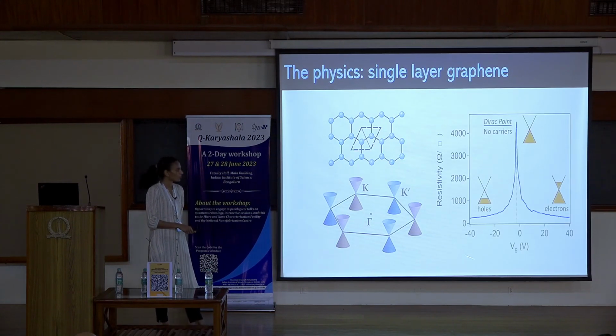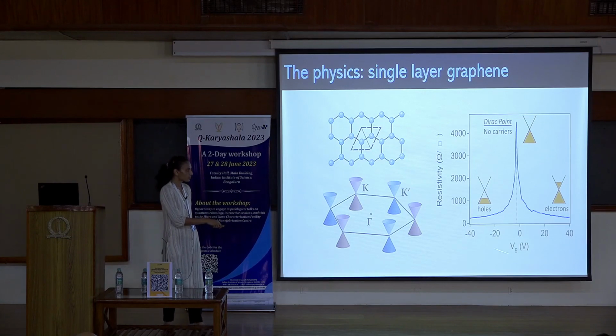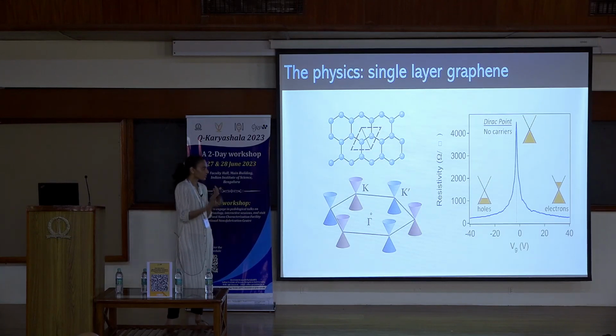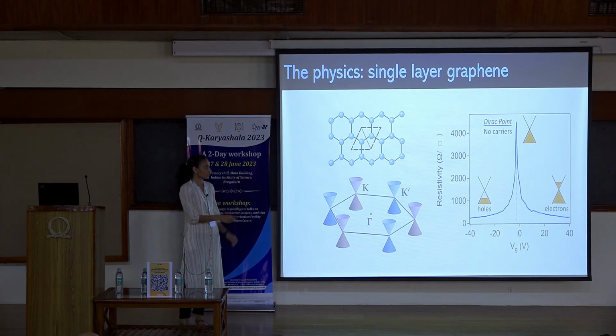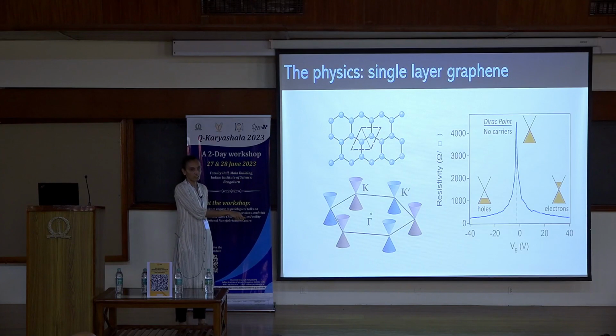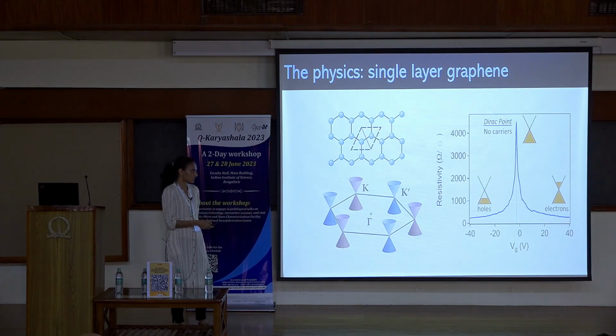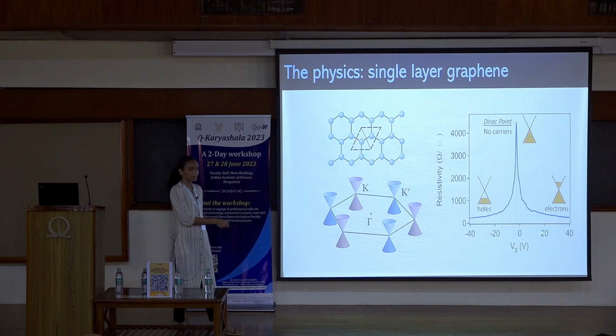In terms of measurements that I told you about, if you measure the resistivity as a function of gate voltage, what I mean by gate voltage is you can manipulate the charge carriers in the system. So if you apply a positive gate voltage, what you're doing is you're populating the conduction band. So you have electrons in your system, or your charge carriers are basically electrons. Now, in case of silicon, you can't change the carriers. You do it by doping, right? You put in boron or whatever dopants you put will determine whether it is N-type or P-type. The advantage of using graphene is that just by simply applying a gate voltage, you can change from electrons to holes. It's just this special band structure that it has where it is touching. With a gate voltage, you can manipulate this.